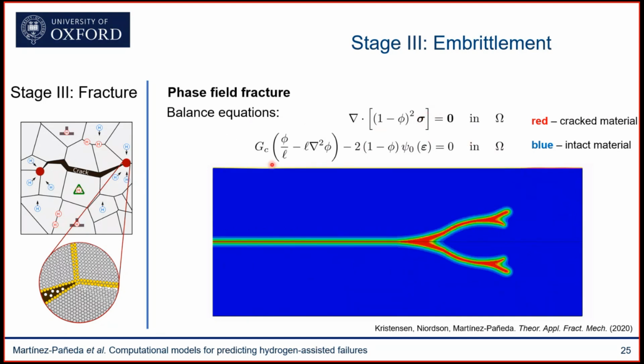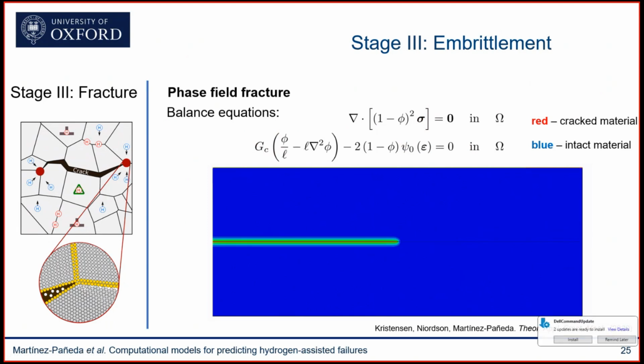And then you have an equation for the evolution of the phase field, which is essentially a competition between the energy stored in the material, the strain energy density, and the fracture energy, the energy required to create new surfaces, a material property that you can measure. And just by solving this additional differential equation, we're able to predict fracture problems of arbitrary complexity.